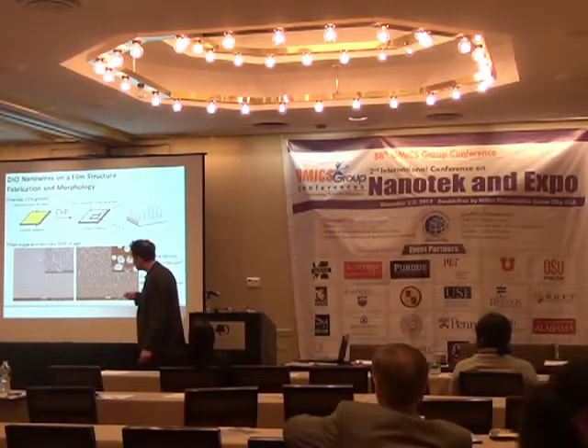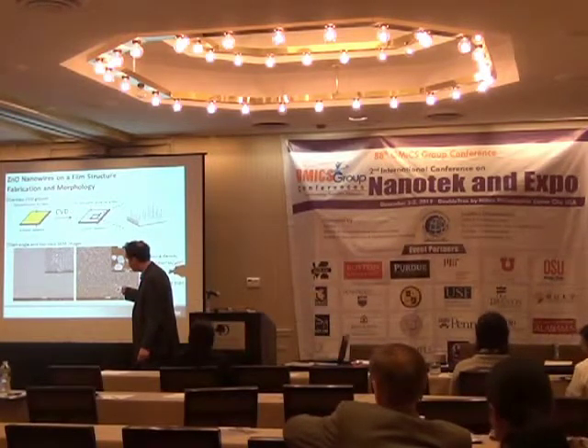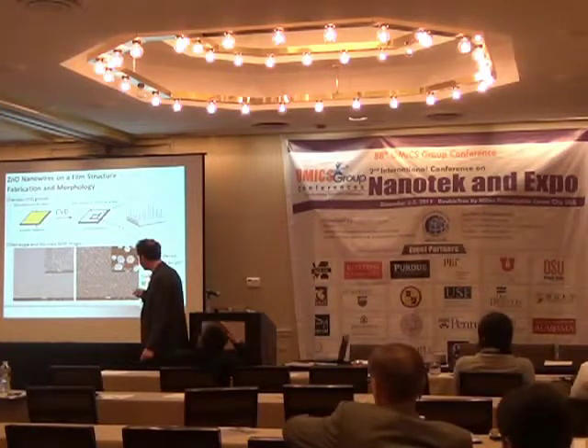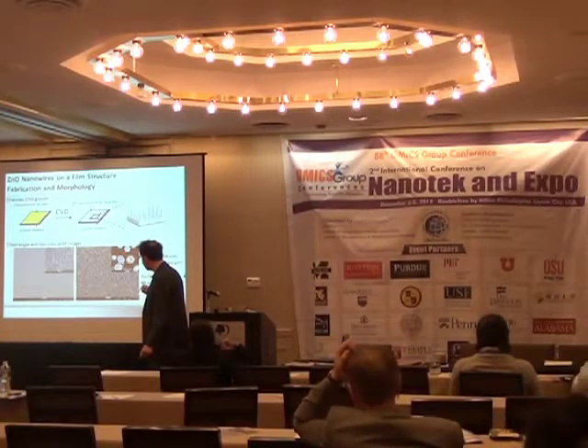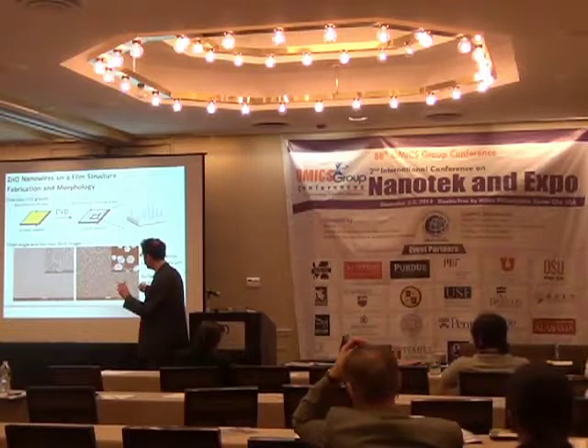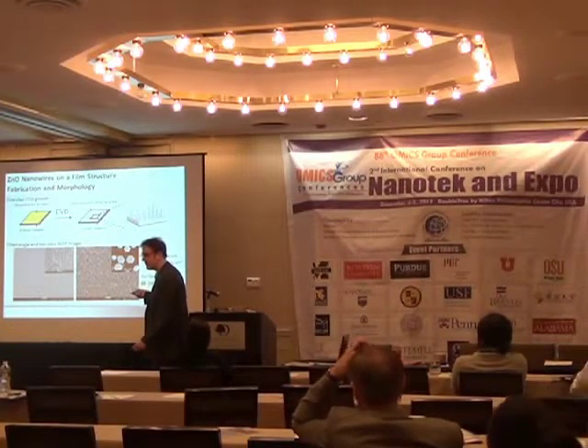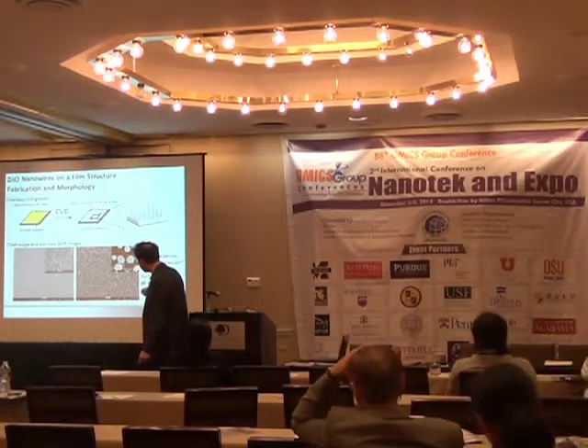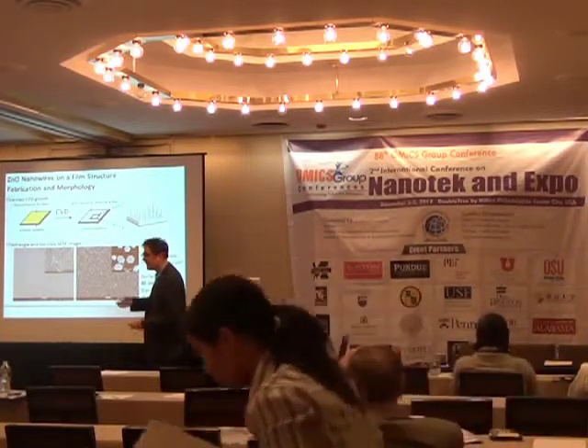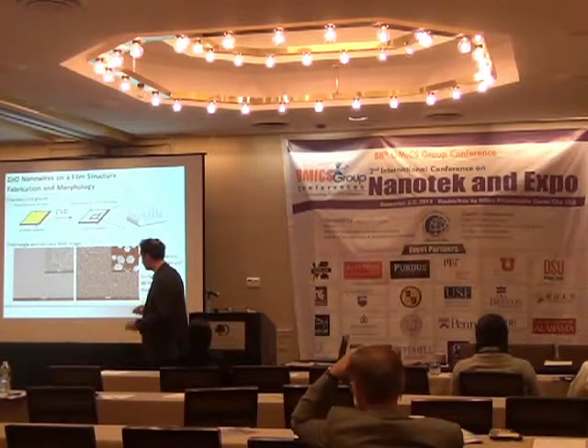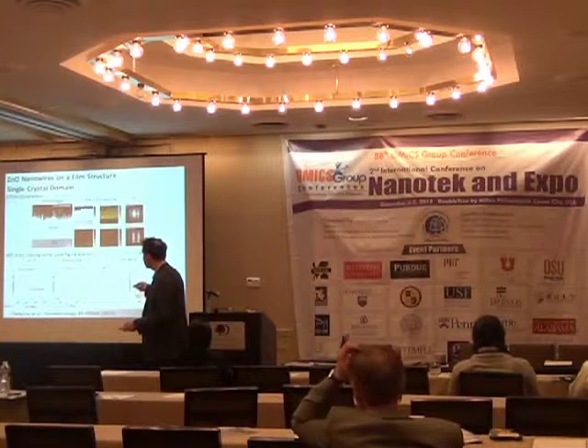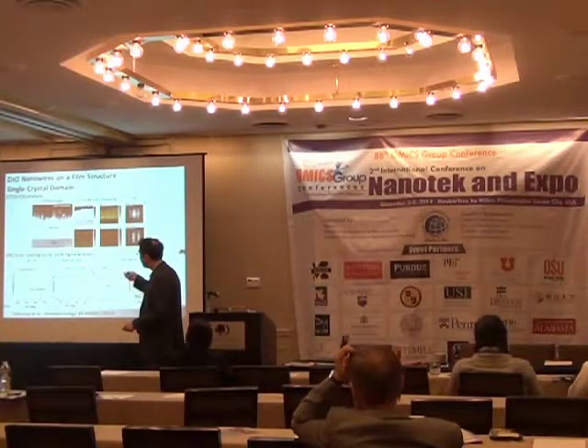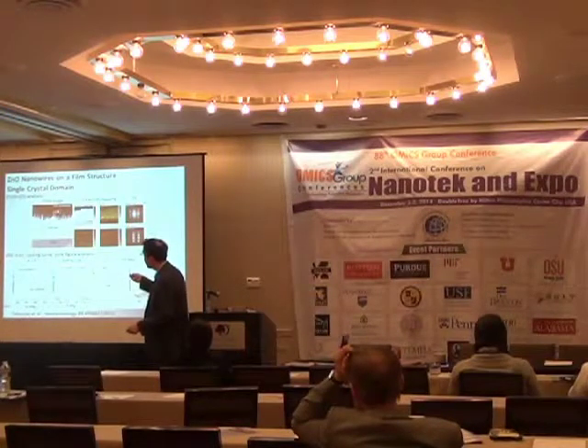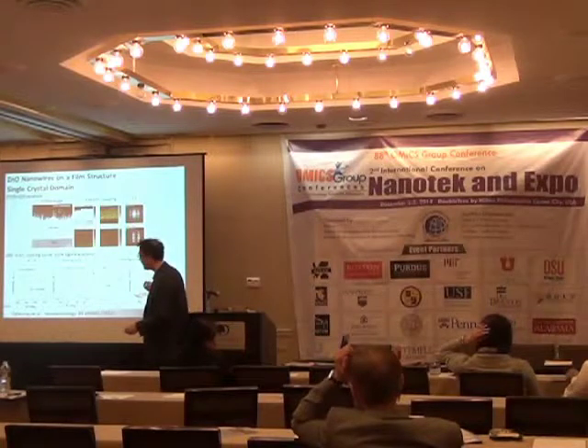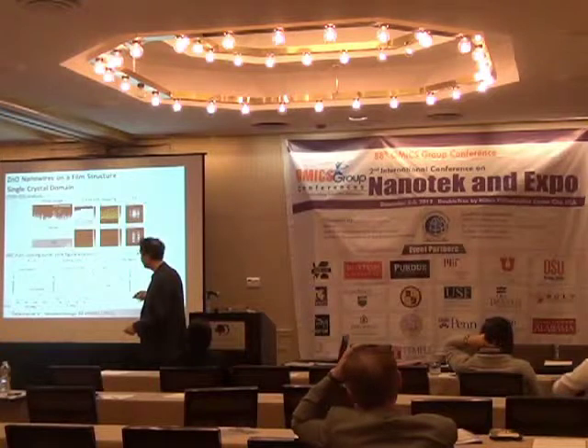So shown here is the field of view of the result of the growth. You can see many nanowires vertically aligned with quite high density, and this is the top view of the same sample, where you see that the top of the nanowires has a beautiful hexagonal shape, which is the shape of the crystal actually, and all facets are perfectly aligned. So this is a good indication of epitaxial growth actually. So they are all aligned. Okay, so it's likely it's epitaxial growth. Good. And the proof of that is by doing electron diffraction analysis. So we have the cross section here, the substrate, the thick layer, nanowires, and when you do electron diffraction of the layer and of the nanowires, you get the same diffraction pattern.